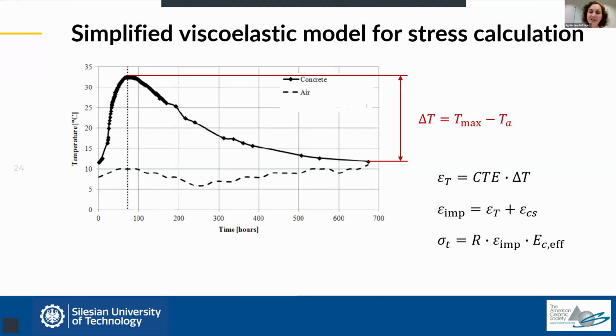So we can say that stress depends directly on strain, and the proportionality constant, according to Hooke's law, is the modulus of elasticity, but we don't use the full modulus of elasticity. We use the so-called effective modulus of elasticity, which represents the effect of creep. So this modulus is much smaller than the actual modulus of elasticity. As a result, the actual stress will be smaller than in a typical linear analysis. I mean, the effect of creep reduces the stress.